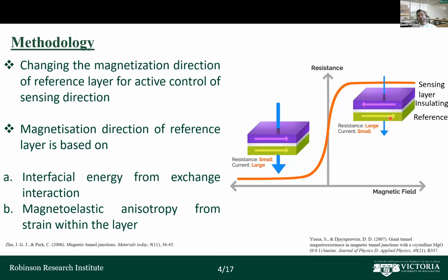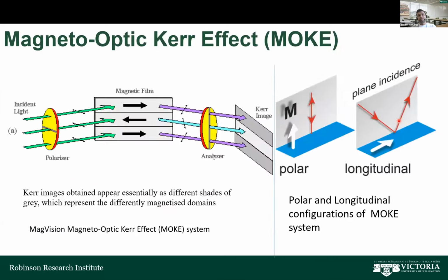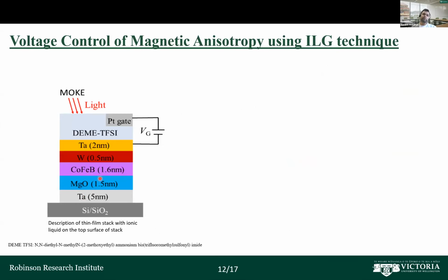Here, as you can see, the thin film stack that I am using is just a half stack. It is not a full magnetic tunneling junction, but here we were able to show that we can tune the anisotropy of this half stack, and we want to incorporate this in the full stack, and then apply voltage and change the sensing direction of the sensor. All right, Usama, I hope that answers your question.